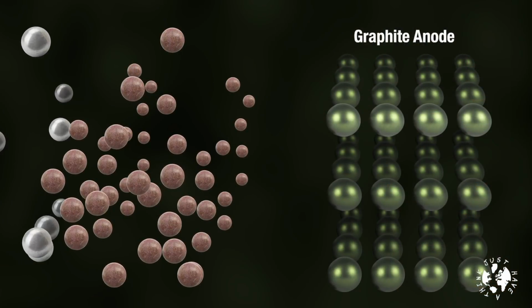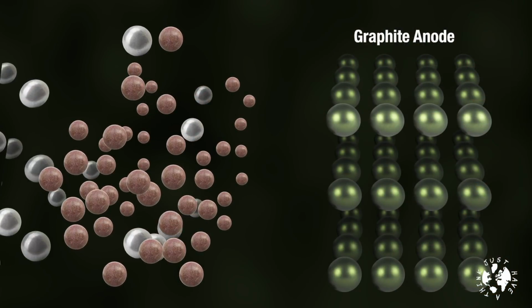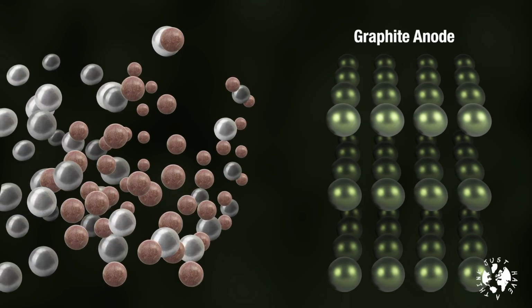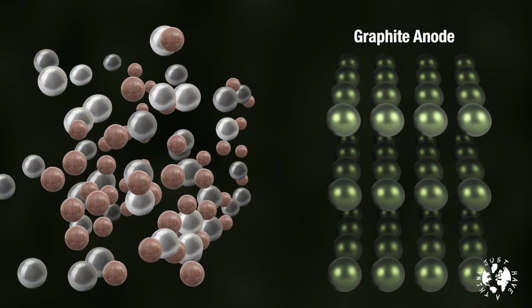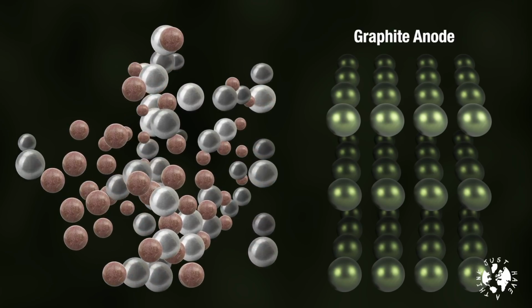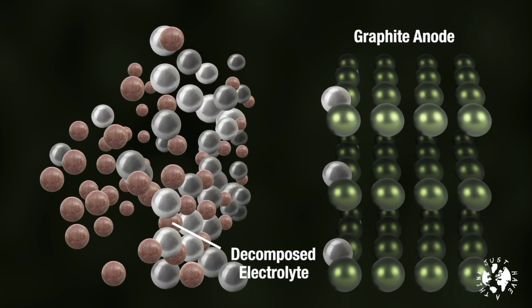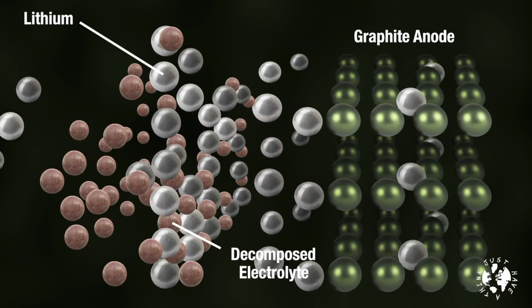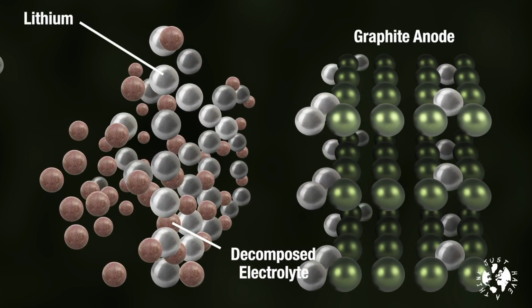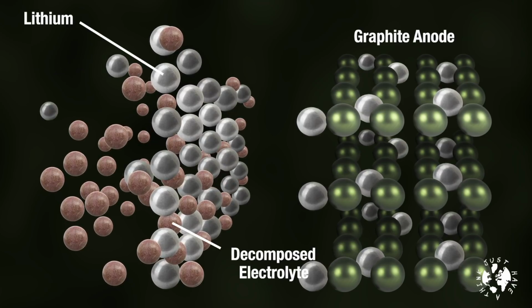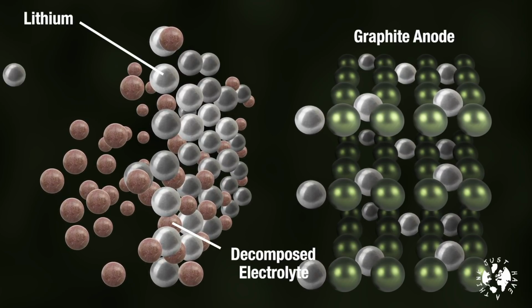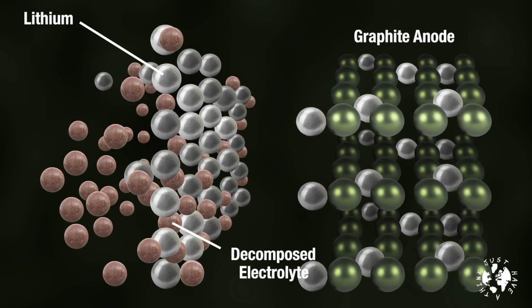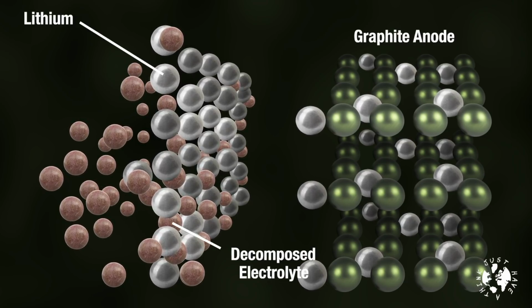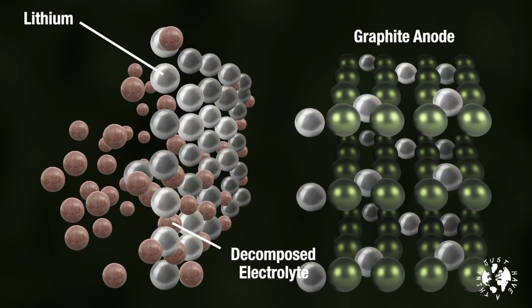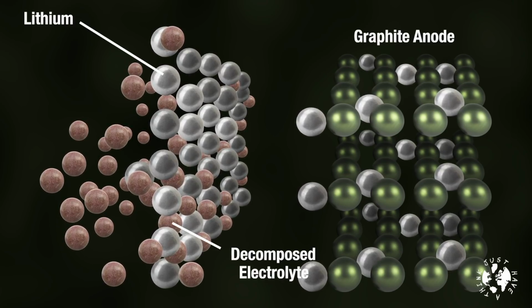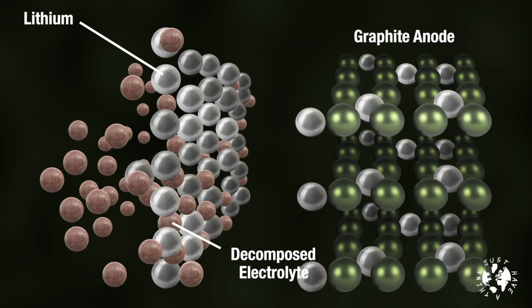In this case, the increase of temperature causes an acceleration of something called solid electrolyte interphase growth, or SEI. And that's a completely new layer inside the cell made up of bits of decomposed electrolyte and bits of lithium. As this layer grows, it uses lithium up, and that causes yet more reduction in battery capacity. So yet again, we get back to the generally accepted view that lithium-ion batteries work best and last longest if they're kept at room temperature, which is why the Department of Energy made the cooling of battery cells one of the priority objectives in their 10-minute charging challenge.